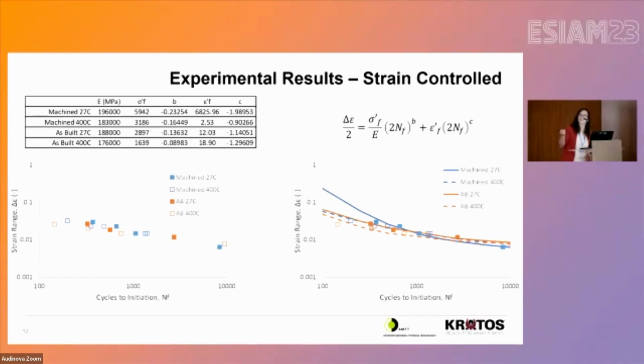So the first is our machined room temperature response, which you would expect to be the baseline. This is our best, our ideal scenario. A smooth specimen at room temperature manifests with this response. The interesting thing is that even though some of these other plots here demonstrate 2 different things that you expect to have knockdowns, so as built, surface condition, or elevated temperature, you seem to get the same life debit associated with both. So that's what I'm trying to demonstrate here in terms of the 2 families.